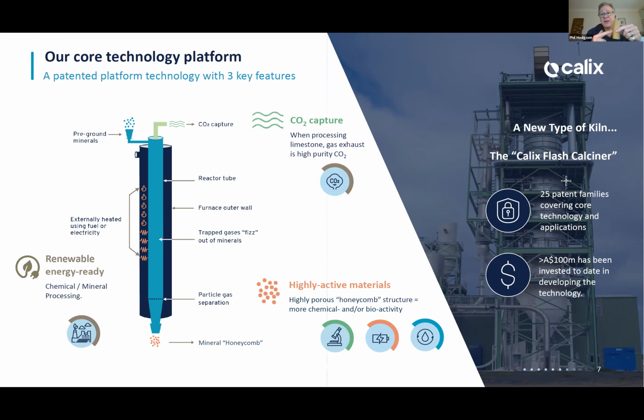And whatever we're trying to heat up, we grind to quite a small particle size. Imagine holding a lump of flour in your hand, that sort of particle size. And imagine just dropping that flour to the floor and watching it float down. Well, that's all that happens inside our tube. We just drop whatever we're trying to heat up in a powder form, and it floats down through the tube. We heat the tube to 1,000 degrees centigrade, and the radiative heat from the red hot walls of that tube radiates into the powder, and that's how we heat it up. So we keep the furnace gases completely separate from what we're trying to heat up. And that actually has some fundamental advantages over the way it's done currently.